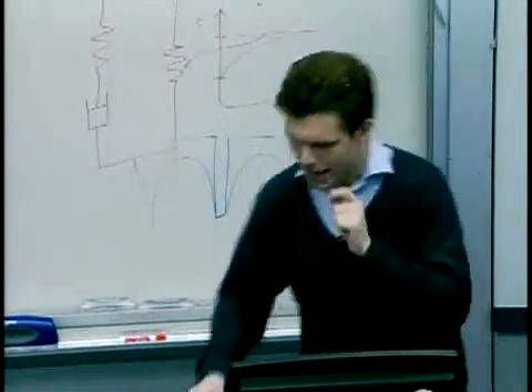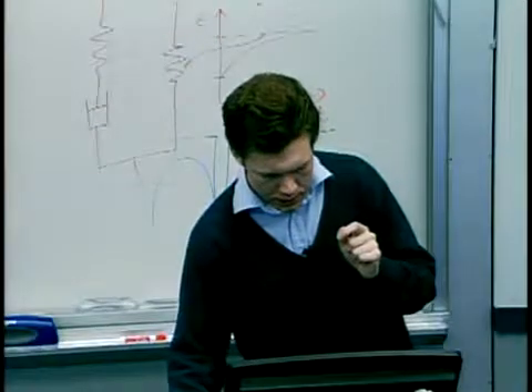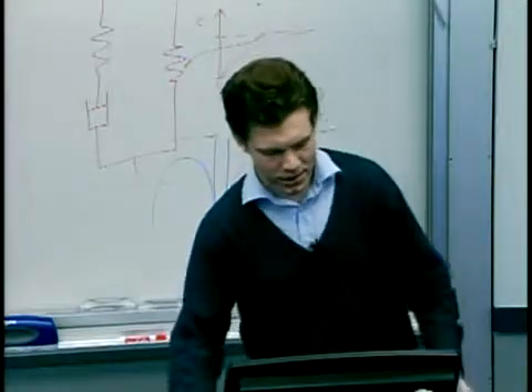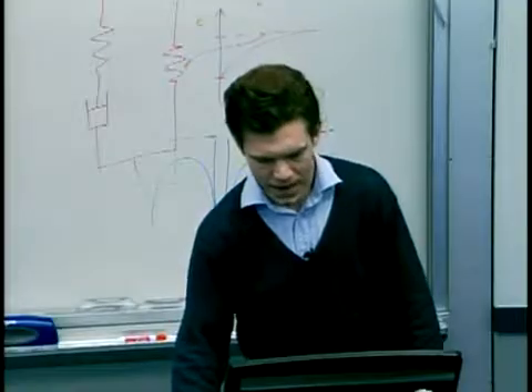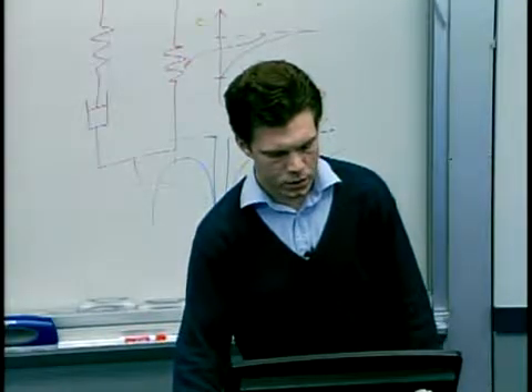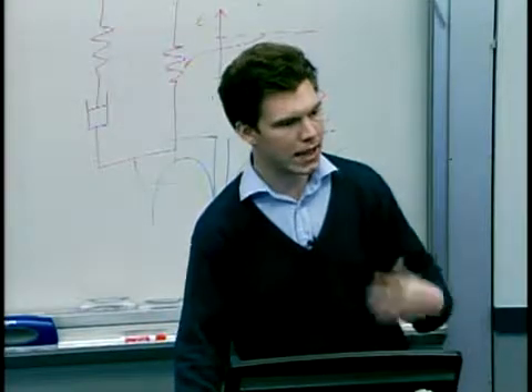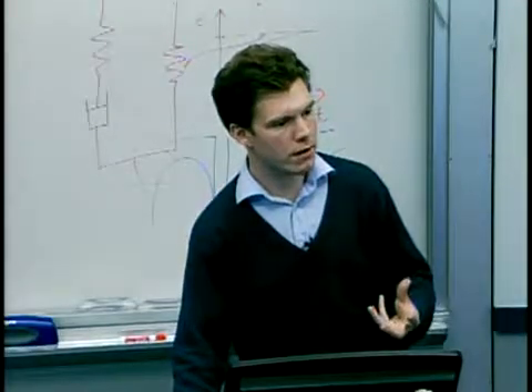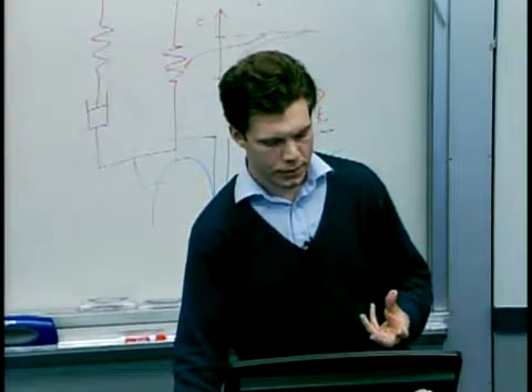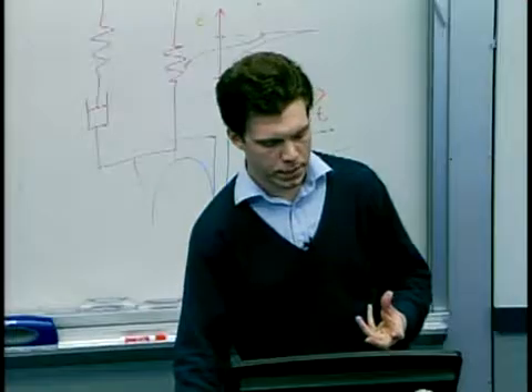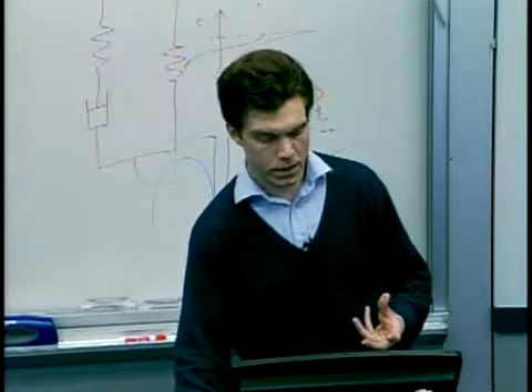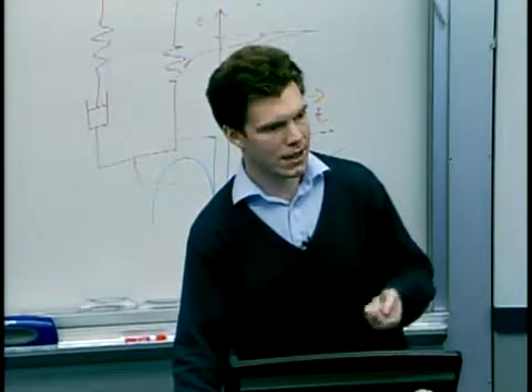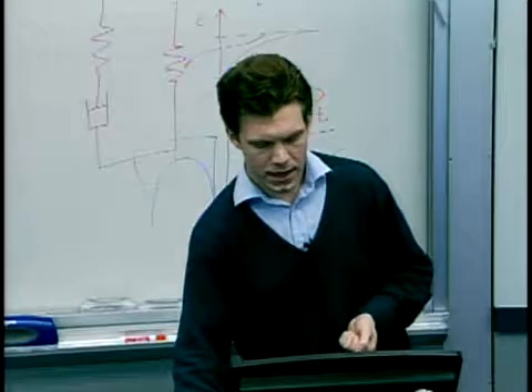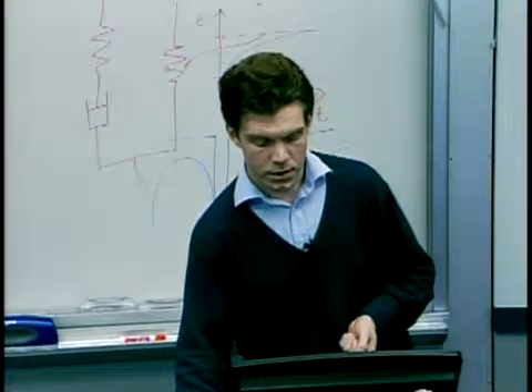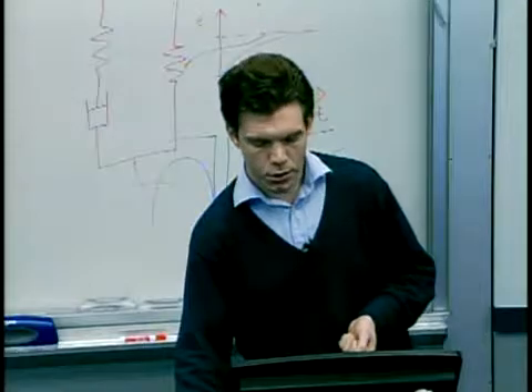Now, here are some 3D plots of results. This is in the top left. This is essentially our standard, our center point run set of parameters, where for a 4-minute hold time you get reasonably good filling of most of the feature sizes, but it's not perfect, so we can get an idea of process variability. This is a set of parameters that was really no use at all.